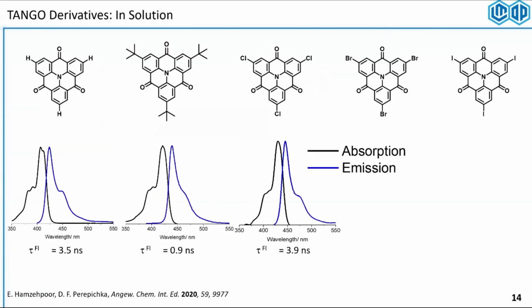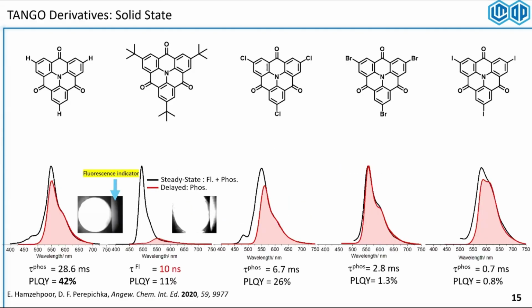So normally, as an organic chemist, I went to the lab and made a bunch of different derivatives to study how this bromine presence is affecting the luminescence. I made different halogens, so chlorine, bromine, iodine, a non-substituted version of Tango, and a tertiary butyl version just for the sake of solubility. These were very flat molecules, not dissolving well. And the ones that I could dissolve, they looked in solution almost identical. Substitution was not really changing much of the emission. They're normal organic fluorescent dyes. But it was in the solid state that the changes started to appear.